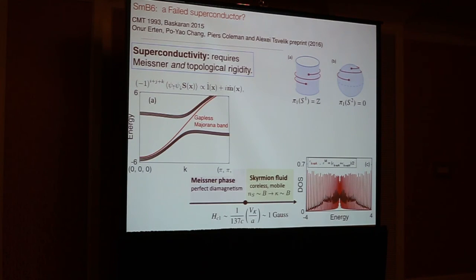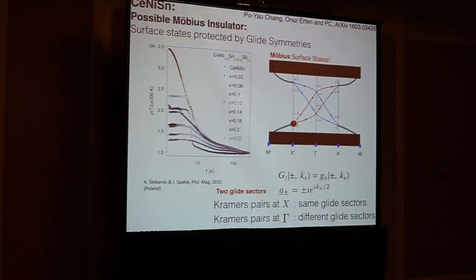Once they condense, they don't like to form a vortex lattice because they have no long-range interactions. And they don't like to get pinned because they have no core. And so rather like the vortex state of the cuprates, they'll form a non-superconducting state. We think that non-superconducting state allows the penetration of electric fields and is therefore a dielectric.